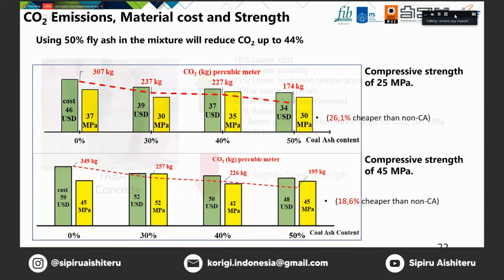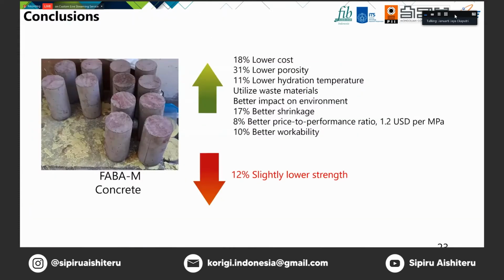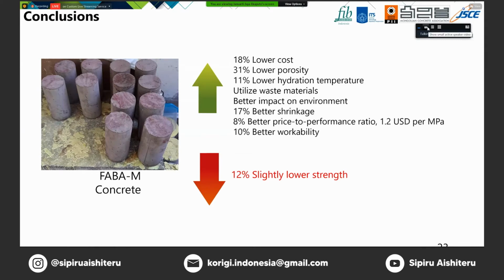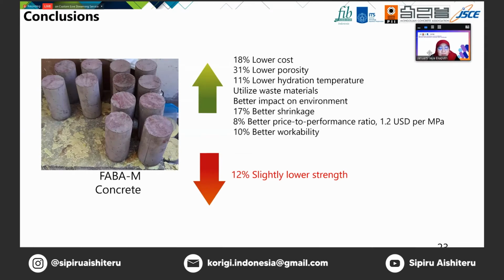And finally, these are the conclusions. As we applied high volume ash in the mixture, we obtained many good results. Even though we have a slightly lower strength, we can manage that in future research. We get a lower cost at least, a denser matrix, low hydration temperature, and better shrinkage. If we control the water content it is very important. And of course, we can contribute to sustainable concrete.